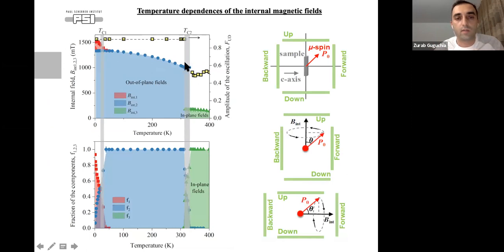And here we have some time average structure, which could be slightly canted, or it could also point along the C-axis, but with lower moment size because it's dynamic. So it basically fluctuates. So we say that only the static C-axis aligned structure we get only at low temperatures, and these fluctuations freeze into this C-axis structure, not directly 100%, but you get some static patches, which grow as a function of lowering temperature.